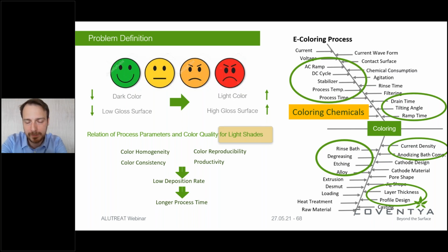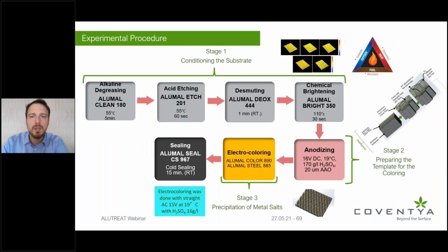So in order to demonstrate this to you, we have devised or structured the test. You can see here at stage 1, we have conditioned the surface with etching and also brightening so that we have with all the samples the same gloss, same surface, and same distribution of the alloying elements. Then we have done exactly the same anodizing cycle with the stabilizer in it. Then we have applied different coloring with nickel-based, which is the ALUMAL STEEL 885, and then ALUMAL COLOR 890.